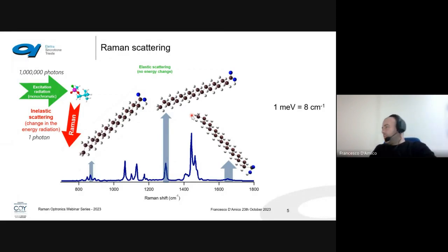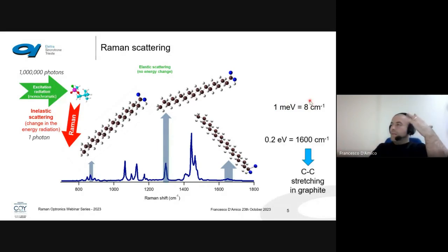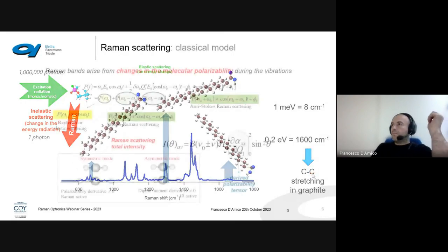About the energy, here we are talking about the Raman shift, which means in inverse centimeters. Just to have an order of magnitude of the energy, 1 milli electron volt corresponds to 8 inverse centimeters. It means that 0.2 electron volts are 1,600 inverse centimeters, which corresponds to the typical stretching in a graphite sample. Visible light and ultraviolet are a few electron volts. Instead, the scattered light is a fraction of electron volts.